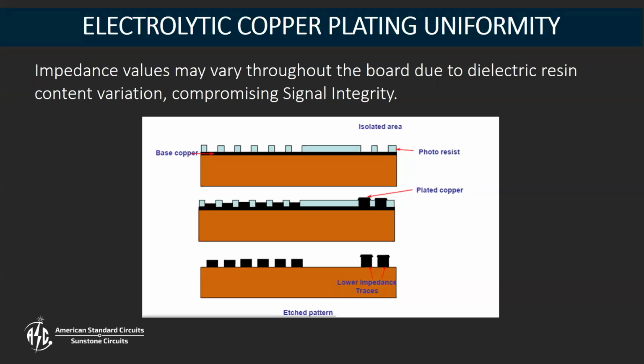In this example, we've got a lot of traces that we're plating on the left side of that board and not a lot on the right side. If you think of it from a physics standpoint, there's more current per square inch going through these traces on the right-hand side of the board as opposed to the left, where it's a little more distributed. As you can see in the middle row there, we get copper height that's about halfway up the photoresist on the left side and over the top of the photoresist on the right side, because we're plating that faster due to the current density. So you actually get variations in height of those copper traces.